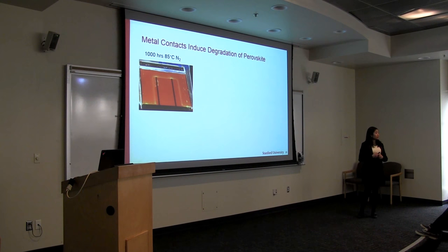First, let's look at the metal-induced degradation. In this case, I took a perovskite solar cell, as shown in this picture, and I aged it for 1,000 hours at 85°C in nitrogen. And we see a clear metal reaction. This is a silver electrode, so I see a reaction between silver and perovskite around here and up there.